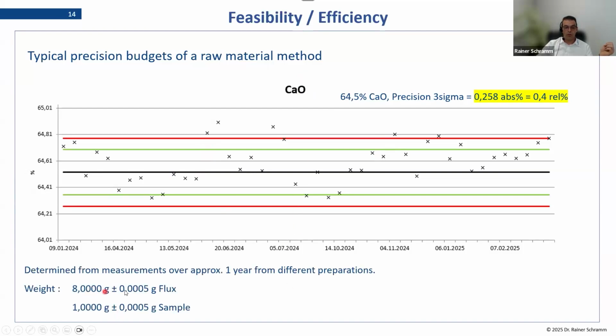And of course, it was always weighed perfectly on the balance, 8 gram flux, 1 gram sample. But the error I see here, I could also convert into a weighing error. And then you see this is about 4 milligram for the sample and about 32 milligram for the 8 gram flux. And there you have a feeling for the real error in the laboratory, and what is it?